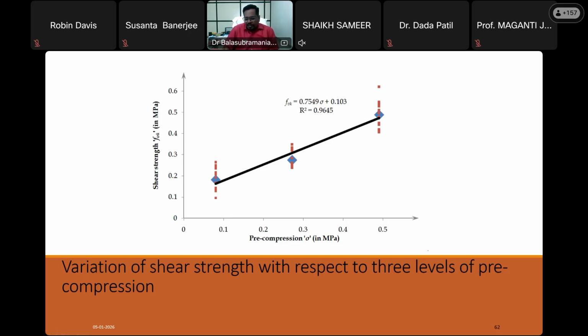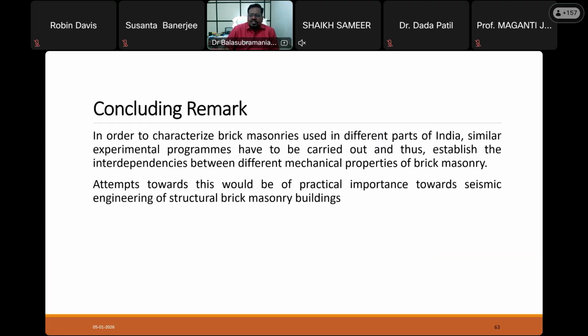But when we are testing some larger specimens, the shear bond and coefficient of friction will come down. In the case of triplet specimen, this is the typical range. Supposing you are testing wallette specimens, the values will be different. Okay.